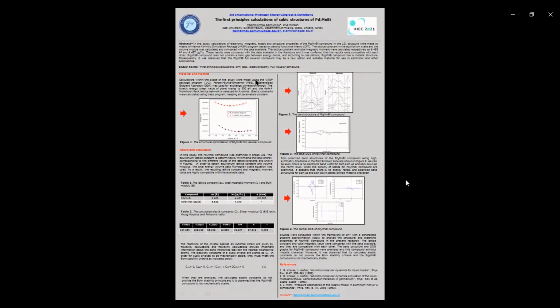The total spin magnetic moment and lattice parameter of the Pd2MnBi compound were obtained as 4.457 Bohr magneton per formula unit and 6.485 angstrom, respectively. In the thesis written by Gilson, only the lattice constant and magnetic moment are calculated. As a result, the resulting lattice constant and magnetic moment values are compatible with the available data. Table 2 shows the calculated elastic constants, shear modulus, B divided by G ratio, Young's modulus, and Poisson ratio.